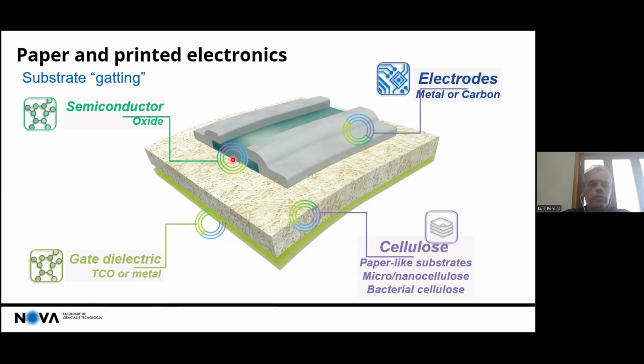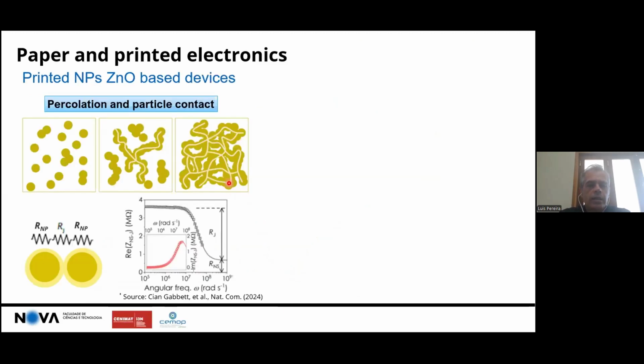On top of the substrate, you need to deposit source and drain contacts that can be metal or carbon. Here we have focused a lot on the oxide semiconductors. And on the back, we have the gate electrode that can also be a TCO, a metal or carbon. So we have different options for these electrodes. Let's start by thinking about the semiconductor layer made of zinc oxide nanoparticles. As I mentioned, you need to ensure you get the percolation path for these particles, so you need a certain concentration of particles to allow it.